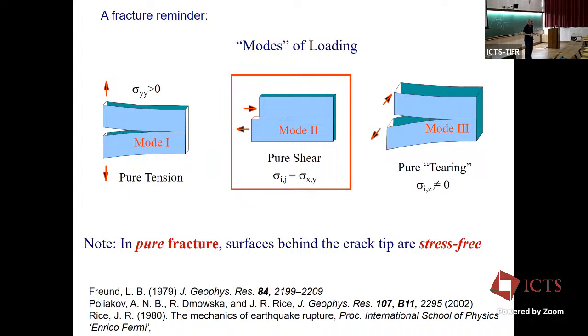I'll remind you, how do we solve this problem to begin with? Well, we have the equations for two uncoupled waves, shear and longitudinal in the bulk, and we couple them on the boundaries. So behind the crack tip are stress-free conditions. There's no stress there because the crack has relieved all the stress. And in front of the crack, we have zero displacement conditions. Nothing's moved yet. And when we solve just the wave equation coupling them to this boundary problem, then we get the square root of r and all this kind of stuff. It's easy to say, it's harder to do, but I'm not going to do it. Just remember. Okay, but anyway, fracture talks about a stress-free boundary.